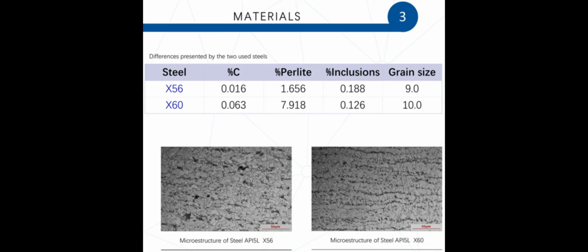The X56 steel, which was steel number one, showed lower content of carbon, pearlite, and inclusions. However, its grain size was large compared to the X60 steel, which, as seen in the image, has a greater homogeneity in microstructure as well as more well-defined pearlite colonies.